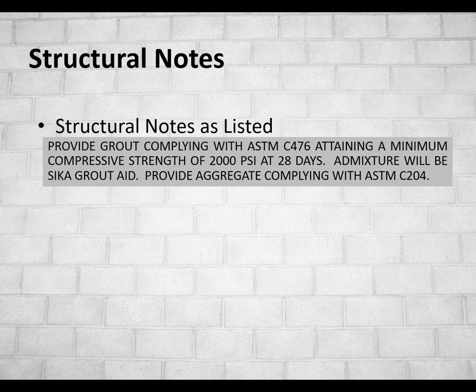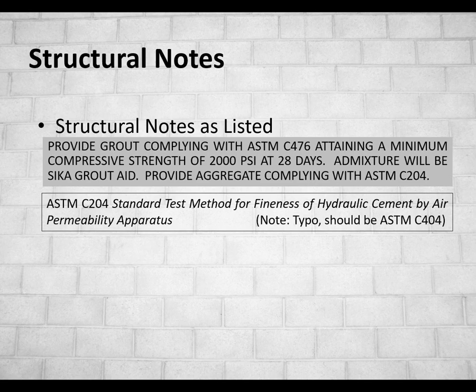Okay, another structural note. Provide grout compliant with ASTM C476. This is my favorite one. Attaining a minimum compressive strength of 2,000 PSI, 28 days with an admixture, and provide aggregate complying with ASTM C204. Remember what I said about cutting and pasting mistakes? Well, here's one. Not the 28 days, although that's not necessary, and not the additive, which is probably not necessary, but the ASTM C204. I looked and looked up what that was. It's standard test method for fineness of hydraulic cement by air permeability apparatus. What they really meant is ASTM C404. It was a typo, but the typos are making themselves from project to project to project.